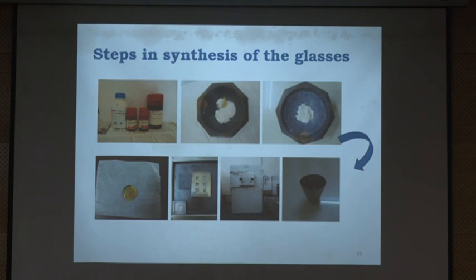So we will weigh the materials individually and grind them with the help of a mortar and pestle. After making a fine powder, we will collect it in a crucible, the platinum crucible, and keep it inside the furnace. We will heat it, and then by the melt quenching technique we are going to make the glass.